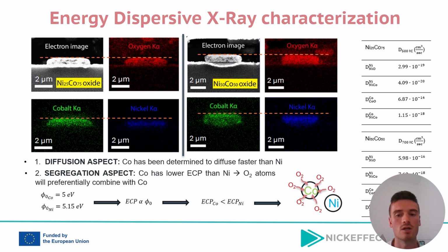EDX maps show elemental distribution, highlighting that cobalt diffuses faster than nickel, eventually impacting the cobalt oxide nickel oxide bilayer segregation taking place. Two main aspects are discussed. From the diffusivity viewpoint, the diffusion rate of cobalt is higher than nickel, as you can see from the values listed at the reference table.